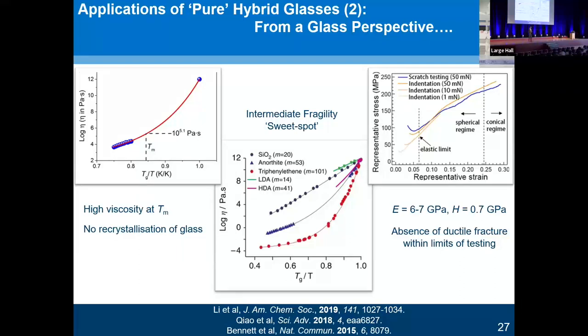They don't recrystallize. And they don't recrystallize because you're going from an open system to a dense liquid. There's no thermodynamic driving force for recrystallization. So that's one good reason. And the other one is their mechanical properties. Inorganic glasses are brittle. We know if we drop our phone screen, it will crack. Organics are ductile, but organics you can scratch really easily.